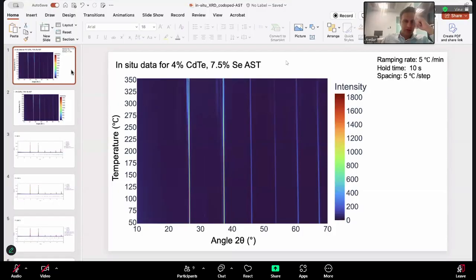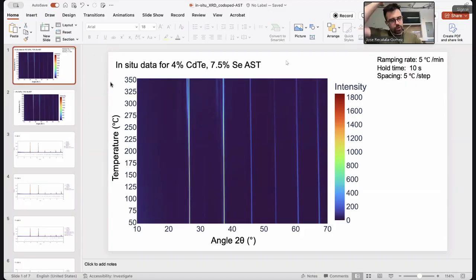Can you go back to the data? Yeah. I just want to see our max temperature was 575 Kelvin for thermoelectrics. But we could go higher in temperature, Kedar. I did not, because first of all, I don't want to melt the compound because that would damage the chamber. And also because, quite frankly, this is as much thermoelectric data as we have. So I thought it would be good, but I'm happy to repeat the measurements to higher temperatures if you want.